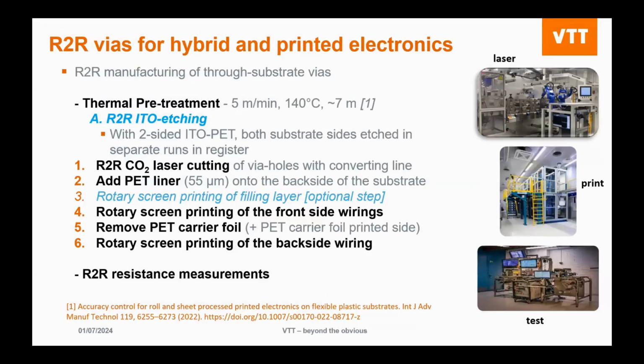But then the question is how to go to volume manufacturing. And so this is where it becomes a little bit more complicated, because there are many steps to get to this double-sided system. And this is just for the double-sided printed silver, or the FPC. The first step we always do when we're doing roll-to-roll processing is the thermal pretreatment. Even though we get our substrates, for instance this Melinex ST506 that's heat stabilized, when you're putting it under tension on a printing line, around 80 newtons of tension, and it goes through the thermal ovens, there's a small percentage of stretching. But one good thing is once you do a thermal pretreatment at that particular condition, if that's the most extreme condition that the substrate is going to see in the roll-to-roll process, it's not going to stretch any further after that.